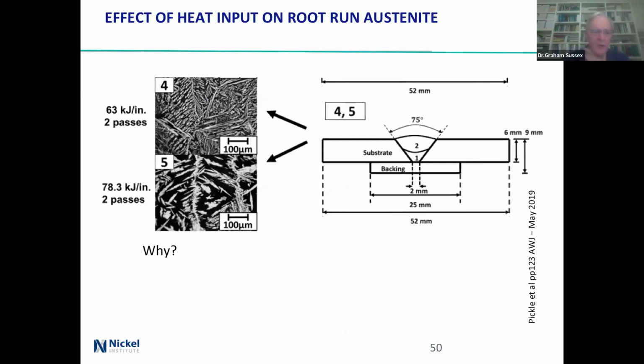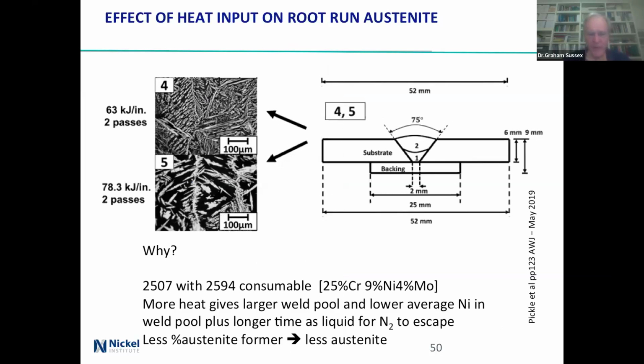And here we've got, yes, 63 kilojoules per inch, 78.3 kilojoules per inch. The Americans will love that. And massively different amounts of austenite. Why? Well, look at what's in there. More heat, larger weld pool, lower average nickel in the weld pool, plus longer time as liquid weld pool, because more power, so the nitrogen can escape. So you get less austenite forming. The things you find when you delve into a weld.